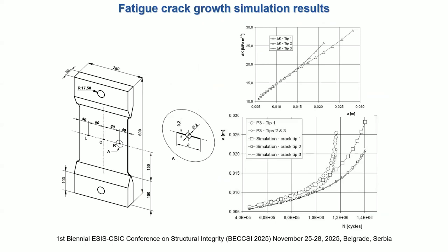Yes. And then we show the results that we have achieved. So for these 3 cracks, we had stress intensity factor ranges shown there. Then we compare simulation results with experimental results. You have this big circle for tip 1 and small circles for average crack length for tip 2 and tip 3. That's for the experiment. And then we have simulation results as rectangular marks. You see that for initial crack lengths we have very nice agreement of results.